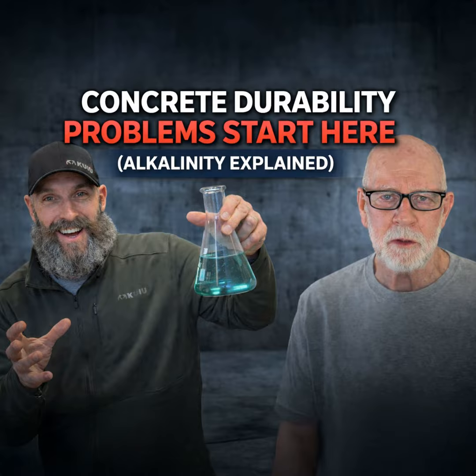So I added more water to the area that wasn't damaged. As I added water to it, it quickly dropped down to a pH of 9. The moderately damaged area, when I added the additional 0.5 milliliter of water, the pH didn't change. Then I did it again. It started to lower. I did it again. Between 5 and 6 times of adding water, it finally went down to 9, because that's basically concrete when it's neutral. When it's fully carbonated, it should be around 9.